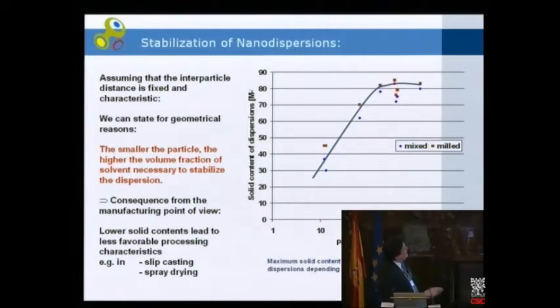And you see, it was not so difficult if we came down from the traditional particle size to the submicron size, but as soon as the powders are smaller than 100 or 80 nanometers, there is a distinct drop in the achievable solid content.